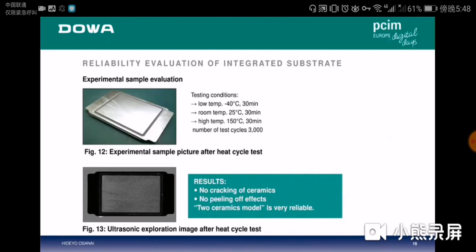This sheet shows the results of the reliability evaluation. We tested samples between minus 40 degrees Celsius and 150 degrees Celsius for 3,000 thermal cycles. We didn't find any cracks in the ceramics or peel-off. It was a very good result.